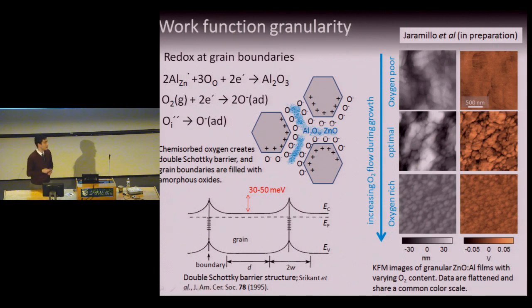It's kind of inverted that way. And this is consistent with what we would expect, because the grain boundaries are high work function elements. The grain boundaries are places which are preferentially oxidized by the ambient environment. Preferential oxidation means the electrochemical potential for electrons is lowered in those regions. Therefore, those regions have higher work function. Those regions also present a barrier to transport.